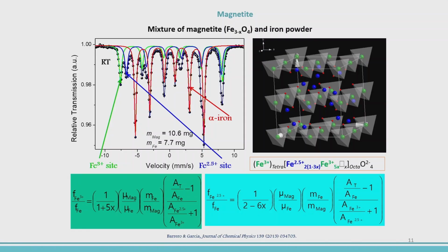And we can find here the relative recoilless F fractions of the iron located on the tetrahedral site divided by the F factor of the reference material that, as I mentioned, is iron powder. So this is the formula. You see here that it depends on X, the molecular weights of the magnetite and the iron powder, the mass that we used to prepare the absorbers, and the areas that are determined from the fitting of the Mossbauer spectra. And this is the formula for the other side. You see? This formula depends on what you guess on the distribution of the iron. Please, this has to be taken into account. If we change this formula, then this formula changes too.